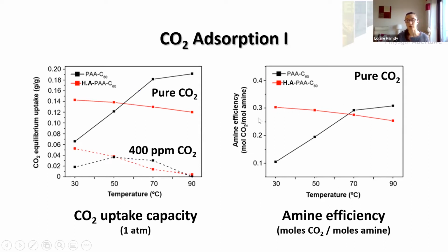And 0.3 amine efficiency means there's 0.3 moles of CO2 adsorbed per mole of amine that we have, and this is high for our polyamine material. We also look at the adsorption under air CO2 concentration, so 400 ppm CO2, and we see that the PAAC60 goes through a maximum temperature, whereby adsorption is highest at 50 degrees.